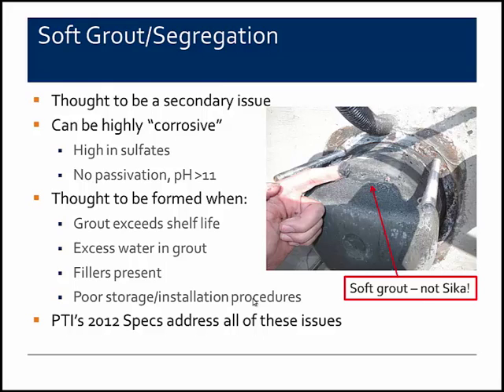There are some theories as to what causes the soft grout to form. We know from testing that if the grout exceeds the shelf life, those dry powdered admixtures that are included in the grout that give it those really nice properties tend to lose their effectiveness, and you can get some irregularities in the mixed grout that can produce this soft grout. We also have determined that excess water, whether it's mixed in or maybe it's in the bottom of the pump or the bottom of the mixer that might get introduced into the grout, can also help produce the soft grout.